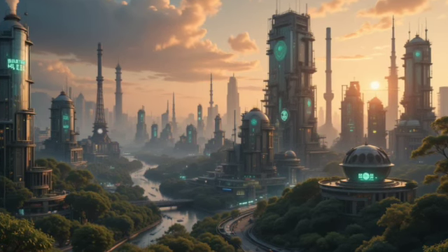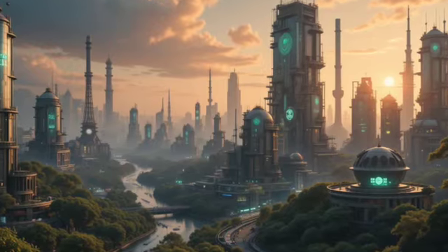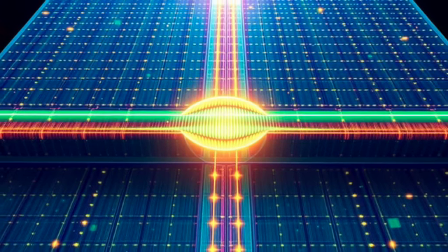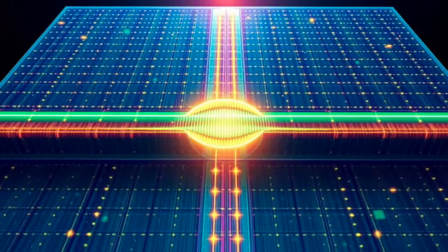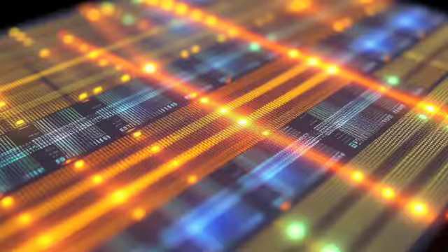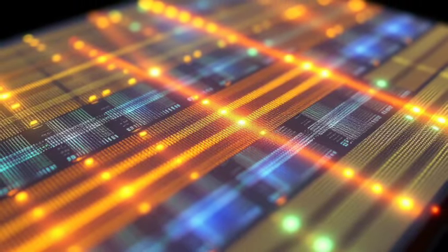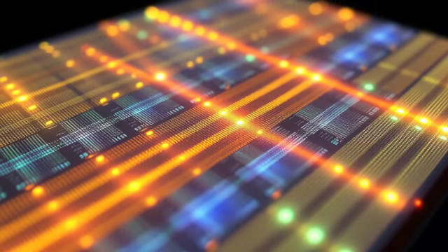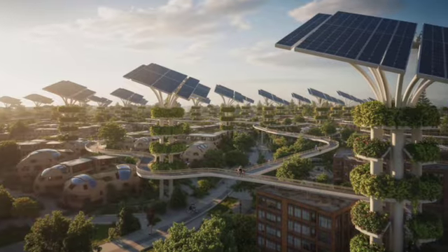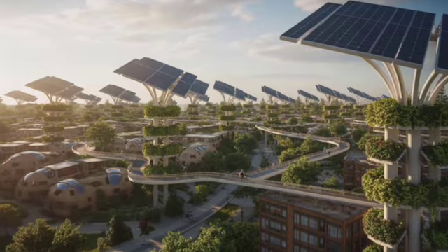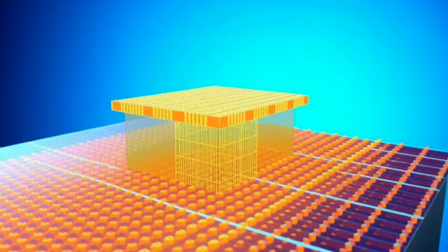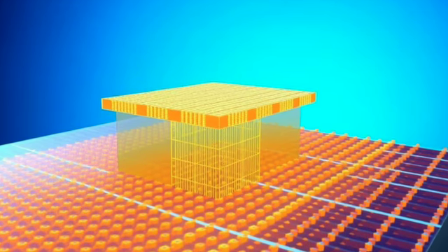Long-term transformative technologies. Hot carrier solar cells. The most fundamental inefficiency in all conventional photovoltaic systems is thermalization. When a photon with energy above the semiconductor bandgap is absorbed, the excess energy above the bandgap is rapidly dissipated as heat within the semiconductor lattice, on a timescale of picoseconds. This thermalization process accounts for the largest single loss mechanism in solar cells, representing roughly 30% of total incident solar energy in a silicon cell.